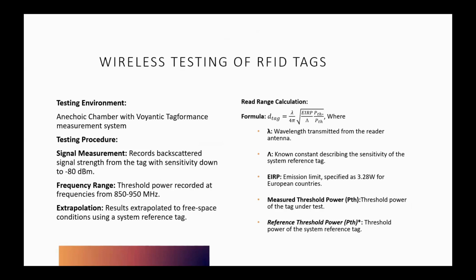So how do we do the testing? We put the RFID tag inside the anechoic chamber and do the measurement using a tag performance measurement system. In this system, we send out a signal and measure the backscatter signal. And we take the measurement from 850 to 950 megahertz. And with this equation, we can measure the read range. Read range gives us the understanding of how far we can read the tag from.